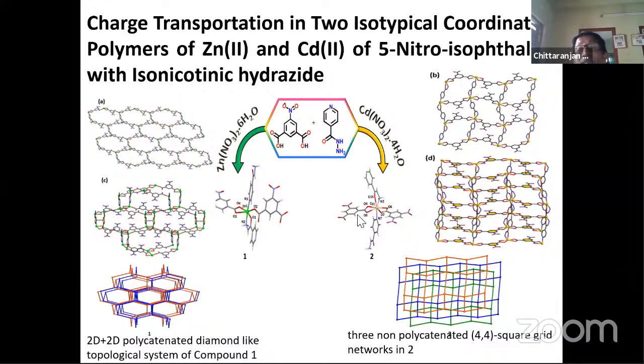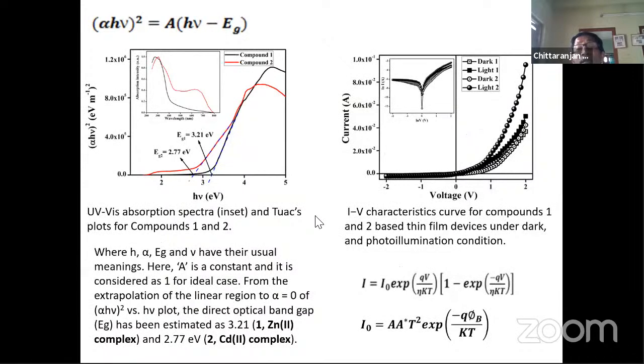So not only the nature of the metal ion or the bridging molecules controls the conductivity, rather the structural pattern also controls the conductivity. Herein also we find that cadmium has better conductivity than the zinc system. It is because of the 4d orbital, which is more delocalized. That may be the reason for the enhancement of conductivity in the cadmium system. But you see the band gap in the cadmium compound is much less than that of the zinc complex. Band gap is 2.77 electron volt in cadmium, while 3.21 in zinc.